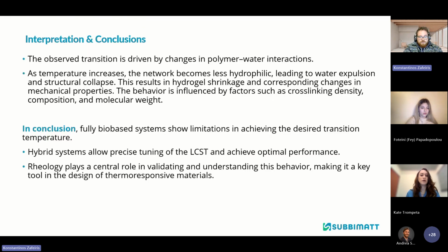So to sum things up, the observed transition is driven by changes in polymer-water interaction. As already noticed, as temperature increases, the network becomes less hydrophilic, leading to shrinkage and changes, of course, in the mechanical properties of the formulation. So in conclusion, fully bio-based systems show limitations when we aim to achieve our desired transition temperature, which is in fact close to the regular body temperature.